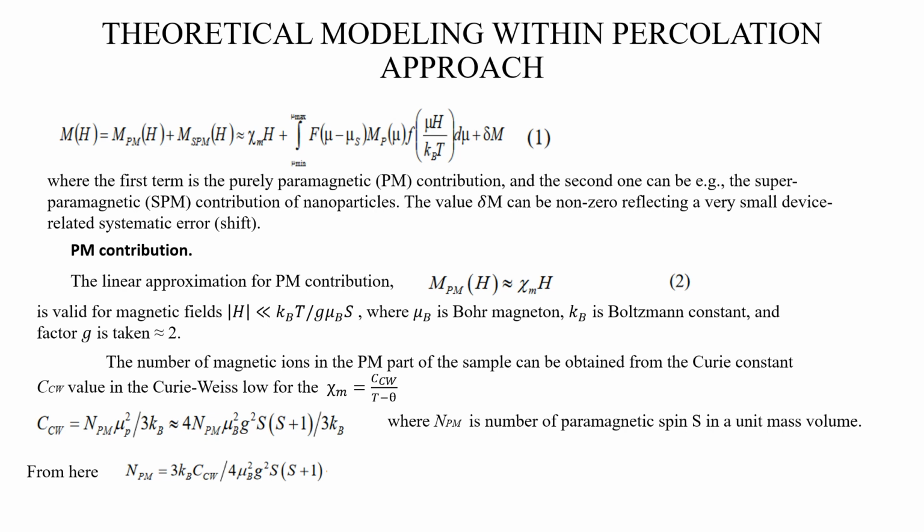To determine a critical concentration of total defects which can lead to the formation of a magnetic response, we use a percolation approach. Using the criteria of percolation theory, it was shown earlier how the percolation threshold of the long-range magnetic order is established mathematically. According to the theory, long-range magnetic order in the system occurs as soon as the infinite cluster forms.